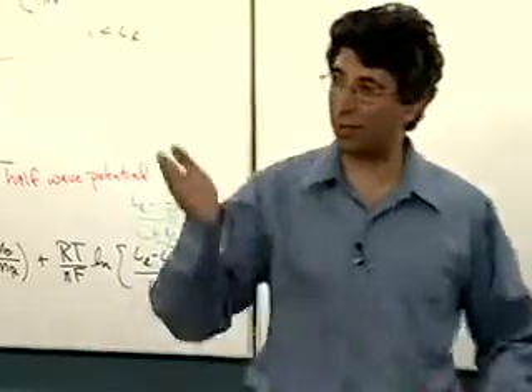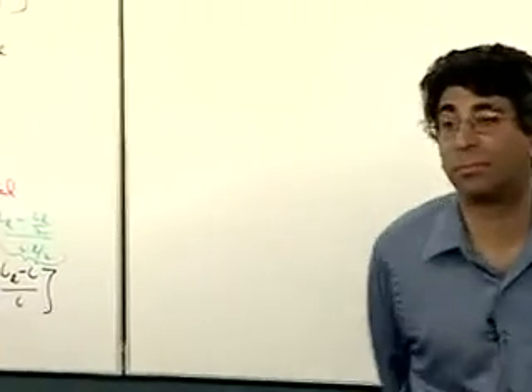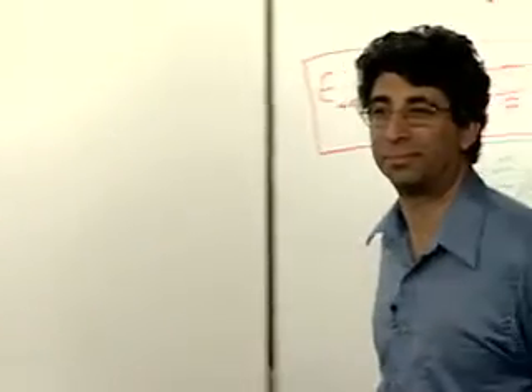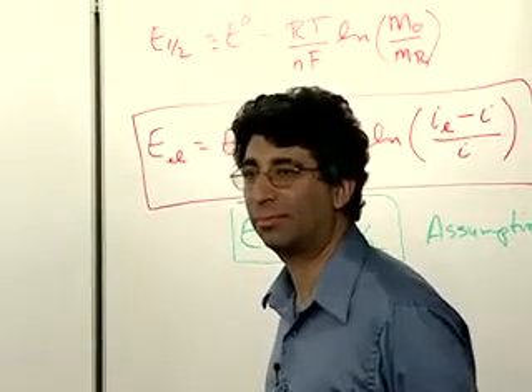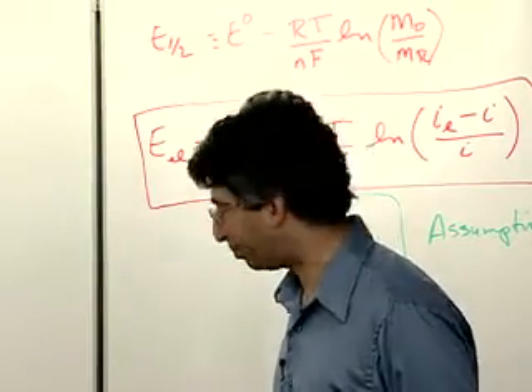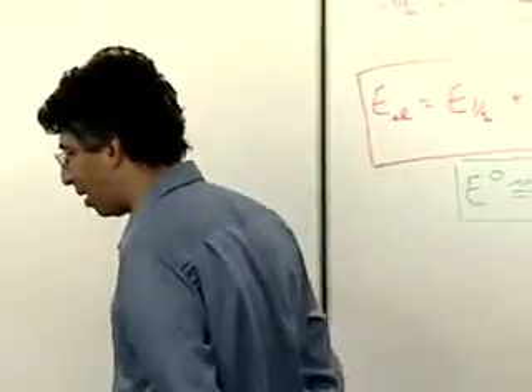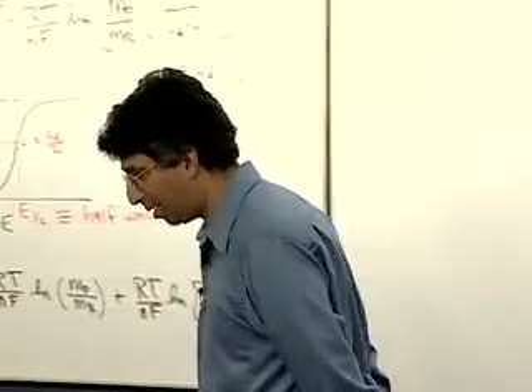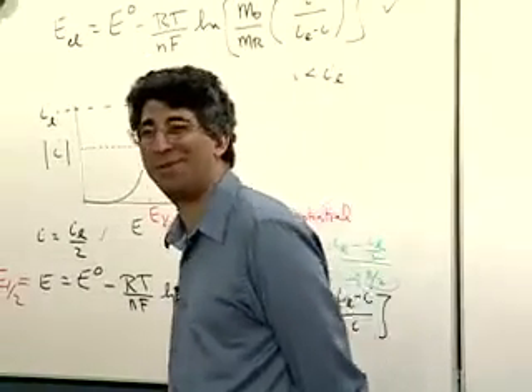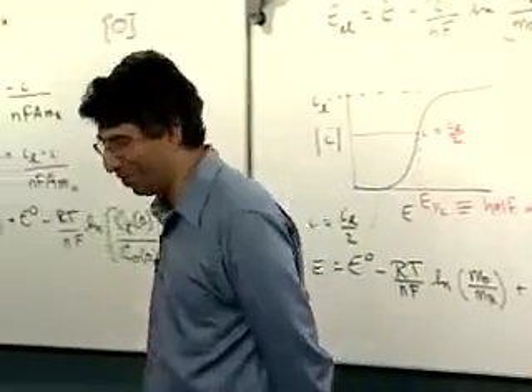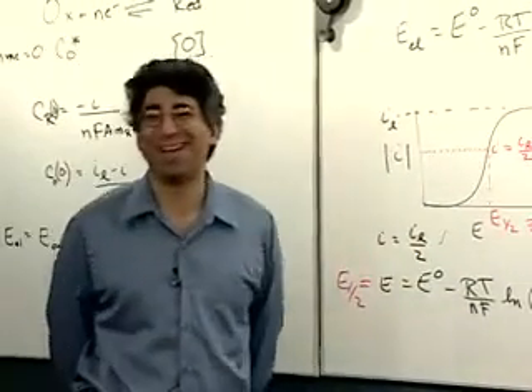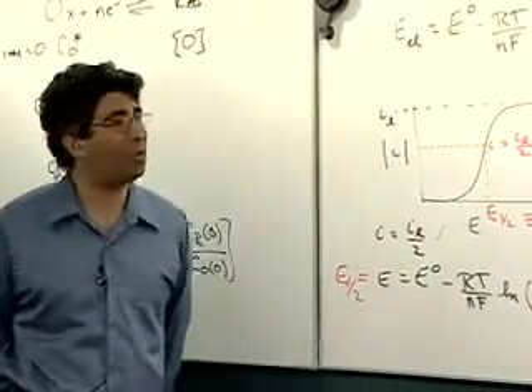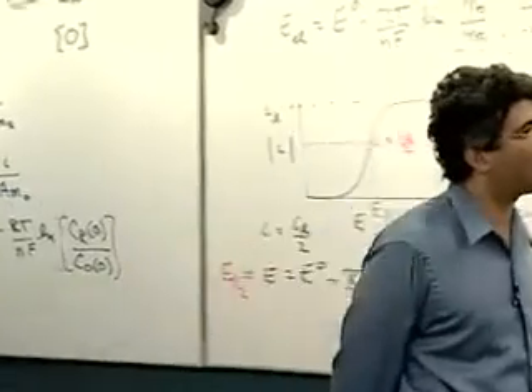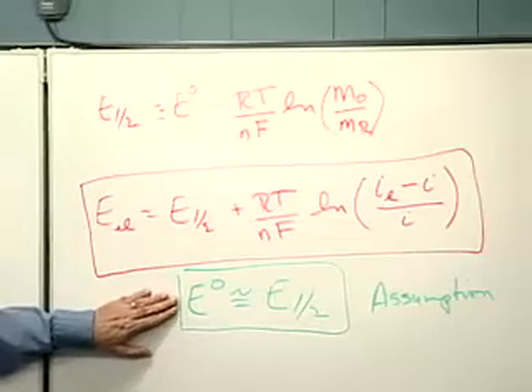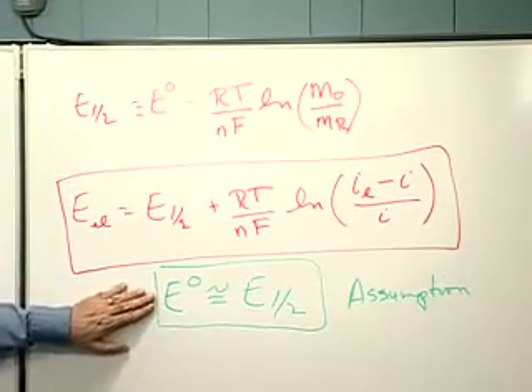OK, now that actually brings it. Yeah. For say ferrocene or something, what is the actual ratio of the oxidized to reduced? The problem is, and you'll appreciate this better than most, Bruce, that measuring diffusion coefficients isn't easy. And so, one of the reasons that this approximation is made is that we typically cannot measure the diffusion coefficient well enough that we could tell that they're different.